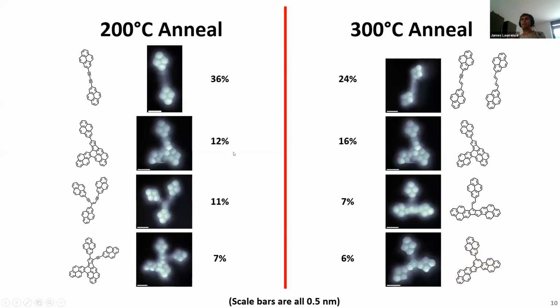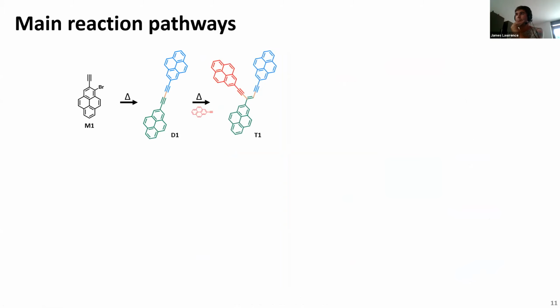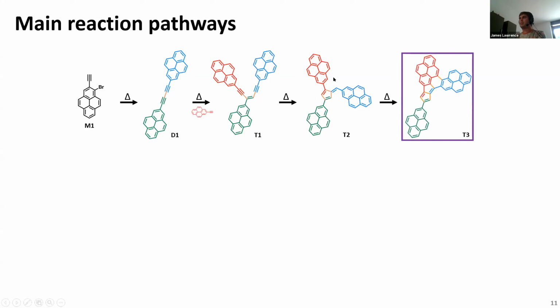So if we try and use this to figure out what the main reaction pathways might be, in a general sort of term, we can think about how this monomer can fuse to form this Glaser coupled dimer. Now after this point, there's various things it can do. But if we look at the most common products, we can see that it can form this open trimer perhaps with the addition of a single monomer, which can then fuse in this central region here with a cycloaddition reaction to form this 5-member ring. And then this in turn can fuse even further with some dehydrogenation to form this fused trimer that I showed on the previous slide.